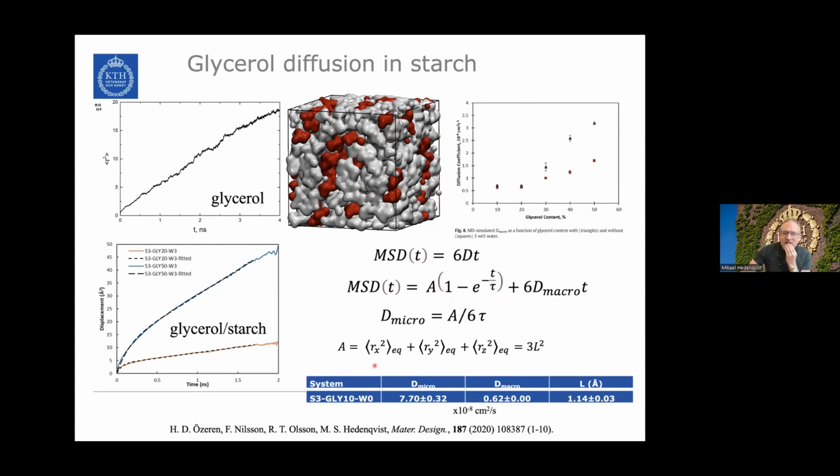And A here is actually related to the box that the molecule moves in. And again, it's a bit exaggerated to call it a box, because if you fit the data, the length of this box is just 1 ångström, and clearly you won't fit a glycerol molecule in that. Nevertheless, it can explain the observations.